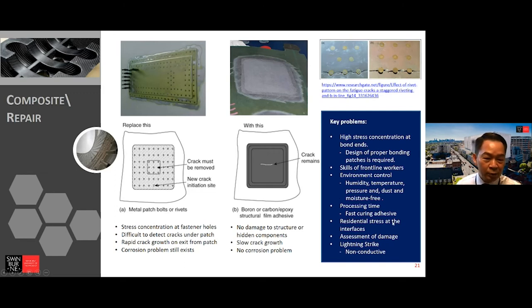Processing time is another problem. That's the reason why I mentioned fast curing resins as one of the big areas we have to look into, because if curing takes too long, no engineering industry would like to use composite material, as they cannot wait too long for the resin to cure. As far as I remember, our team developed resins that can be cured within a few minutes. But then it goes to another problem, which is residual stress. There are a lot of things we still have to do in detail, to make sure this residual stress will not introduce another kind of problem.